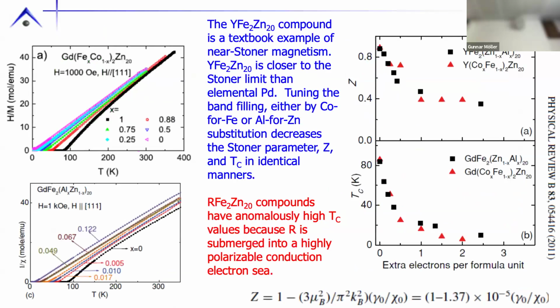Okay. So the Stoner limit, for those not familiar, if you think of the elemental Olympics of ferromagnetism, you have iron, nickel, and cobalt there on the podium, and palladium just missed third place. It's almost ferromagnetic. You can parameterize this: if the Stoner parameter hits 1, it becomes ferromagnetic. If it's less than 1, it's close. And it turns out for yttrium iron 2 zinc 20, you're closer to the Stoner limit than palladium. You have a Stoner parameter, which you can infer from the specific heat and susceptibility, of about 0.9.